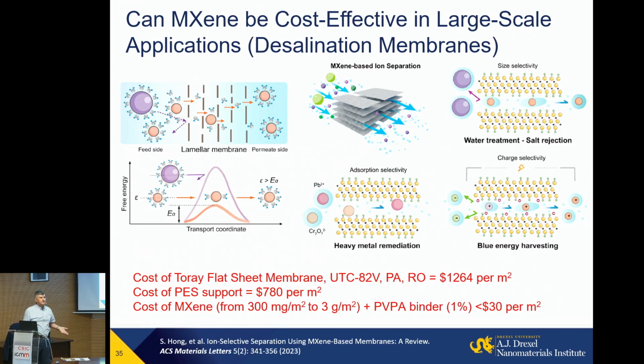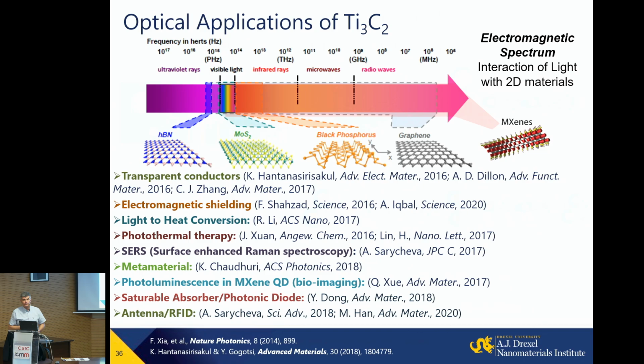There is lots of activity on water desalination, ion separation, gas separation, membranes using a similar principle, because you can do ion sieving, and through spacing between the layers, charge, and also applying potential, you can control transport of ions. Very similarly, you have seen beautiful colors of MXene on a couple of slides before, complementing plasmonic colors of these materials. And they strongly interact with electromagnetic waves from UV to microwaves and radio waves. And this leads to many applications, from light to heat conversion, from photothermal water desalination to cancer treatment, photothermal therapy, to antennas and EMI shielding.